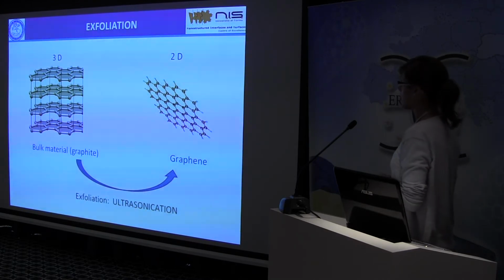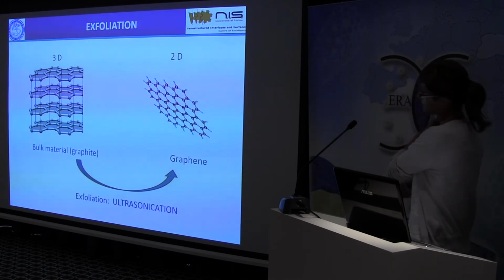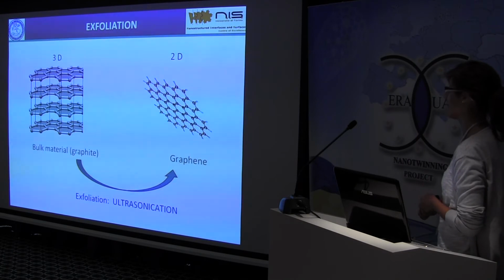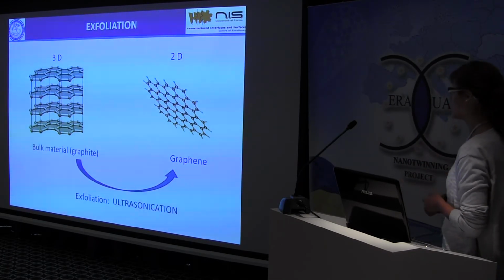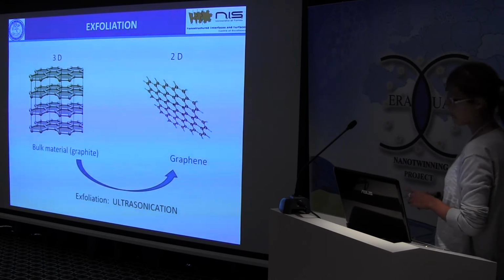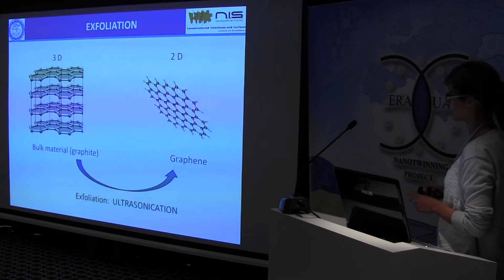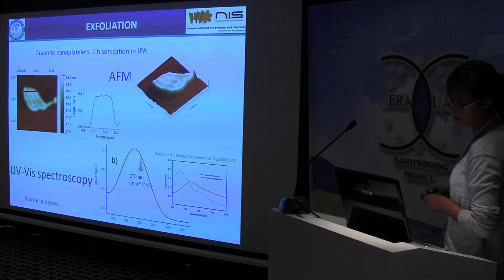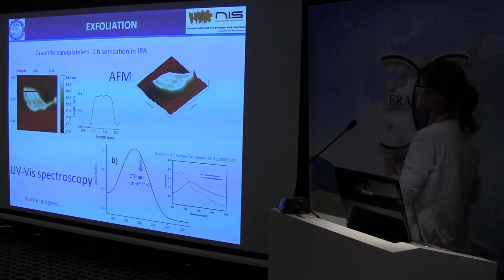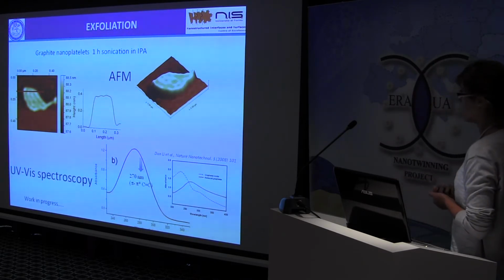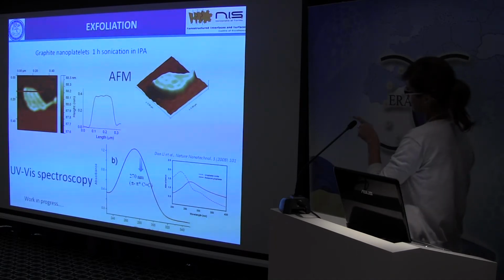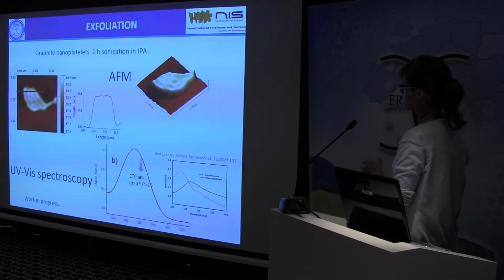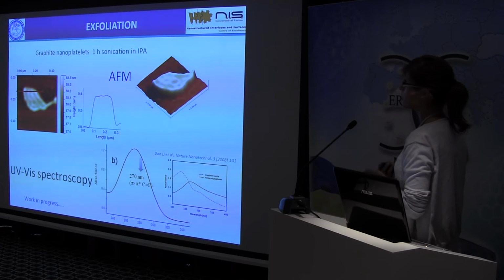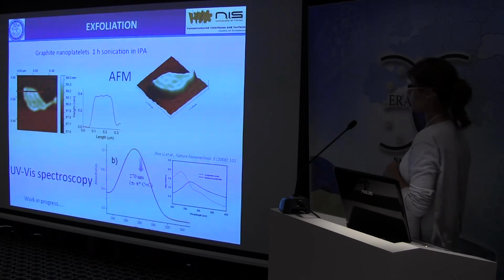In this kind of composite, I used graphite nanoplatelets as filler, but we thought it could be interesting to use an exfoliated material, for example graphene, to enhance the electrical conductivity of these composites. So we tried to obtain graphene from graphite nanoplatelets by ultrasonication. We ultrasonicated the graphite nanoplatelets for 1 hour in isopropanol, and the dispersion obtained was analyzed with AFM. Here you have an image of the platelet, and here you can see its profile. Its height is about 0.4 nanometers, which is very close to the d-spacing of graphite. So we can say that in this image we have almost one-layer graphene.